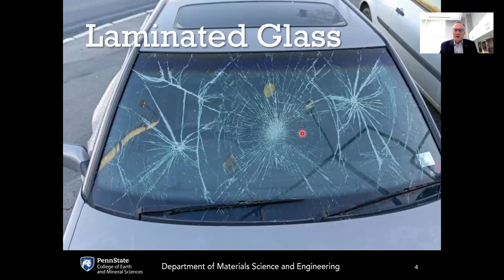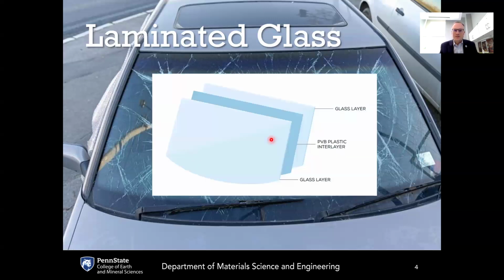All of this damage becomes additional weak points for new cracks to pop in. And so you can have new cracks that go around this initial starburst pattern, and then you have new cracks connecting all of these radially emanating cracks, and that's what can give the spider web type of pattern to breakage in laminated glasses.